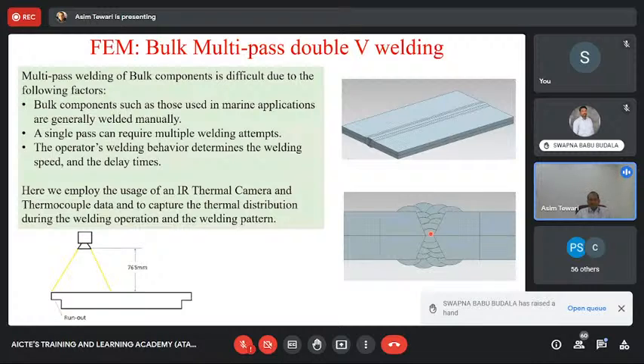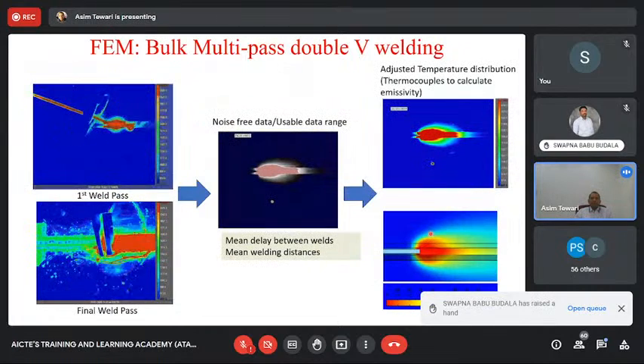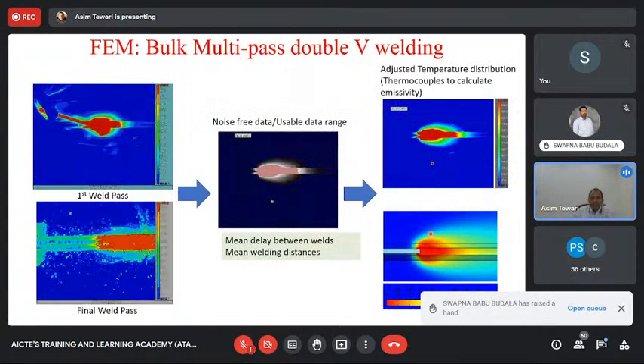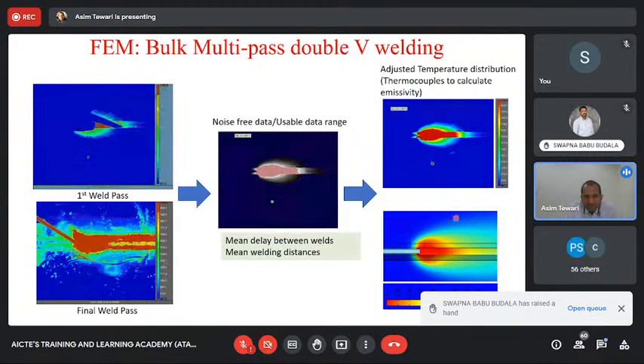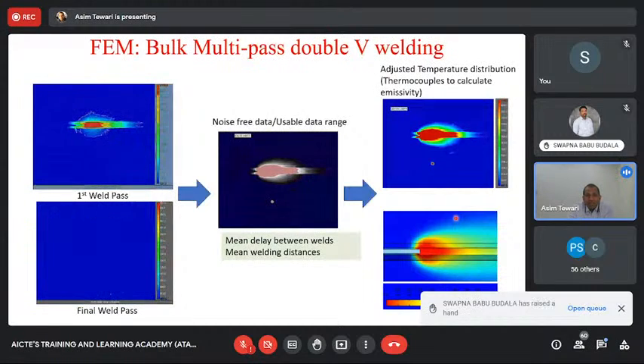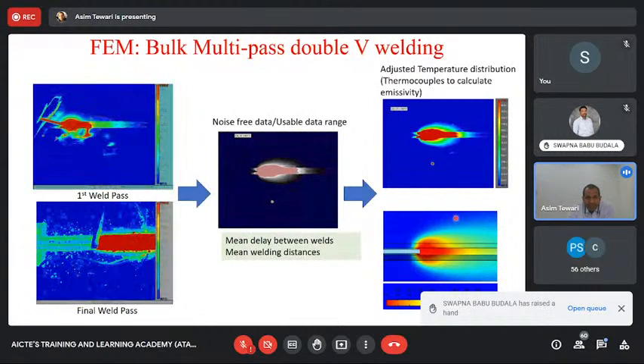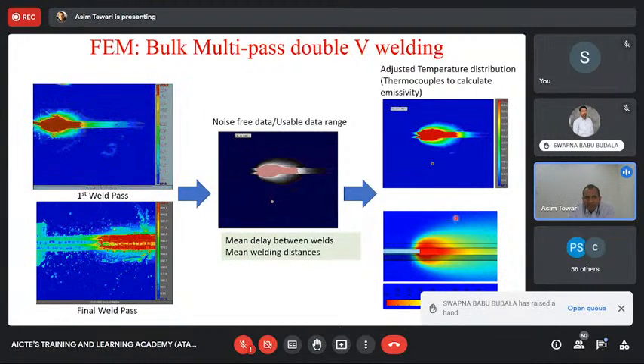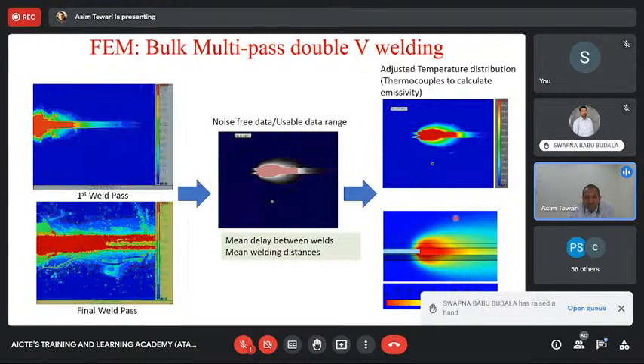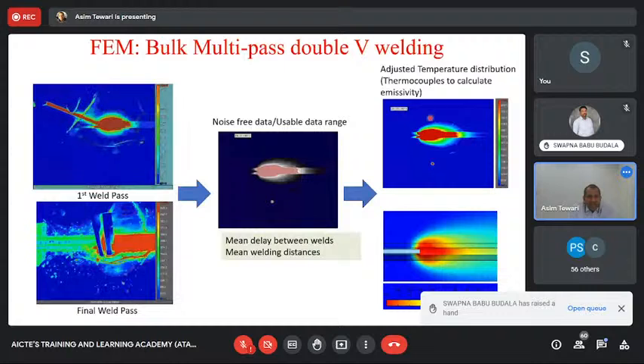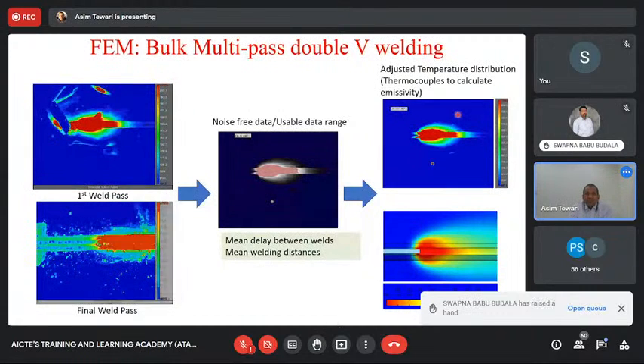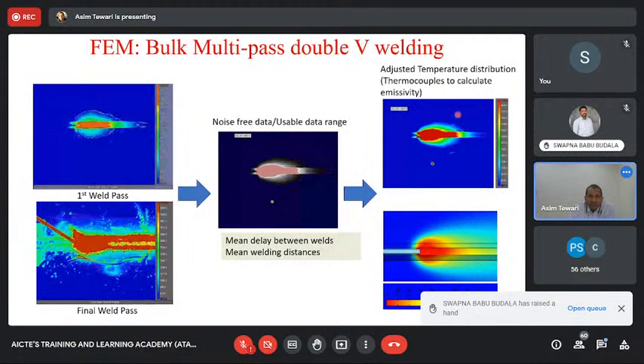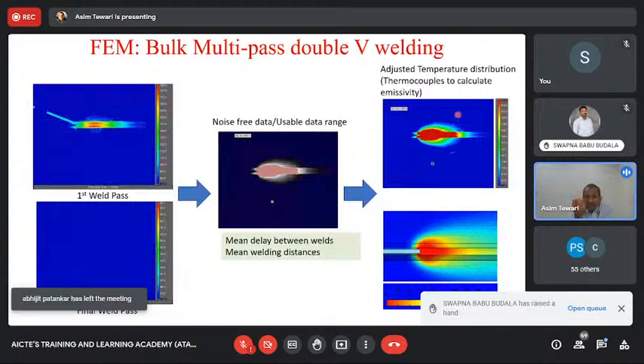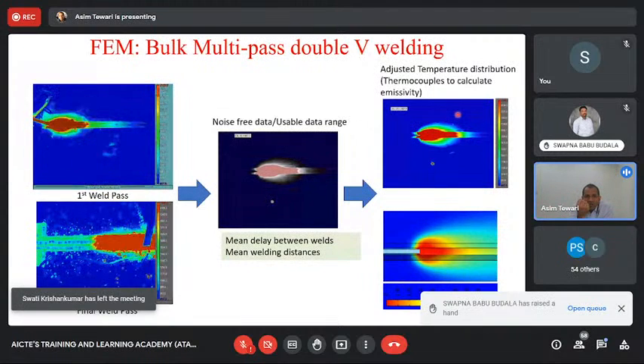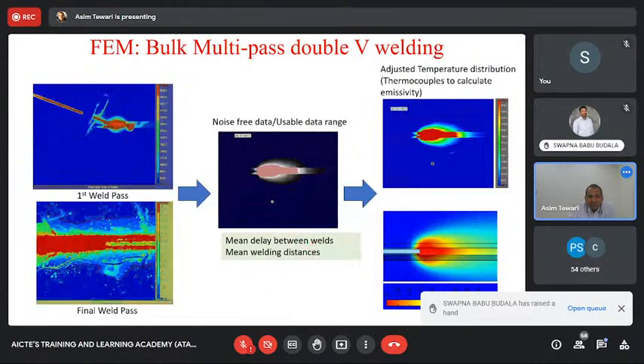And then we had a thermal camera on top, and that thermal camera was capturing the temperature. So what you see on the left hand side are actually the thermal camera images of this material when you are actually doing the welding on it. So these are not simulations, these are actual experimental data. And based on the emissivity of the material, which is, by the way, a non-linear function of temperature, you would be able to create the actual temperature maps of what really happened when you were doing that single bead. So you have now an experimental way to measure the actual temperature which is formed while you are adding a single bead. And the same can, of course, be done through simulations.